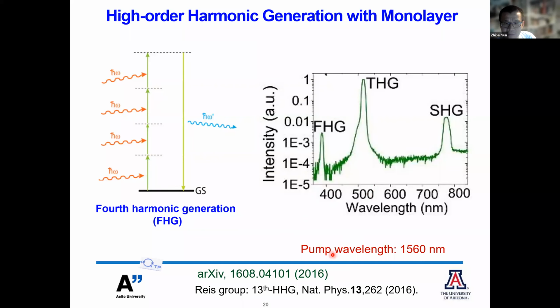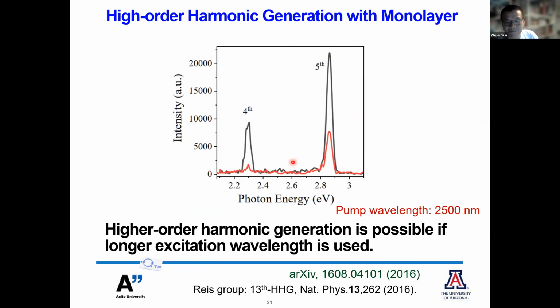Anyway, because we use pump wavelengths around 1560 nanometer, much higher order harmonic generation is in the UV range and not observed. This is because of the strong absorption inside of the MoS2 in this wavelength range. This indicates that if you use a much longer excitation wavelength, then high harmonic generation could be possible. You can see here, if we tune the pump wavelength from 1550 nanometer to 2500 nanometer, we could easily observe the fourth harmonic and also the fifth harmonic generation from the monolayer sample. This has also been reported by the Reis group in the US.